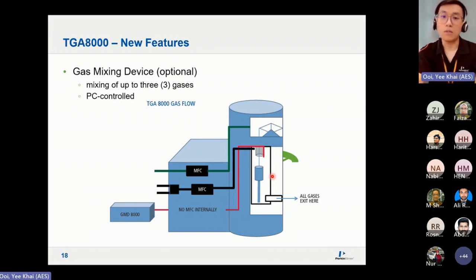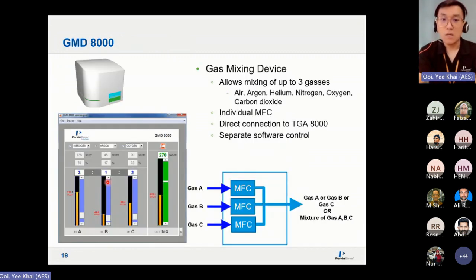what if I want to do multiple gas analysis, or I want to mix my gas in a certain ratio or composition? This allows you to do simulation studies, for example, with different proportions of gas, mixing up to 3 types of gases using this accessory, the GMD 8000. It looks like this. Inside the GMD 8000, there is an individual MFC for each gas. Now you can connect different gases to it. For example, I have nitrogen, argon, and oxygen, and I can control the percentage in the mix. Now, do not confuse this with purified air. Purified air is already pre-blended or pre-mixed, so you cannot control the ratio. Although it is a mixture of gases, the ratio is constant.